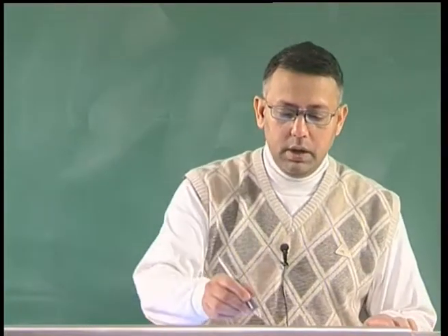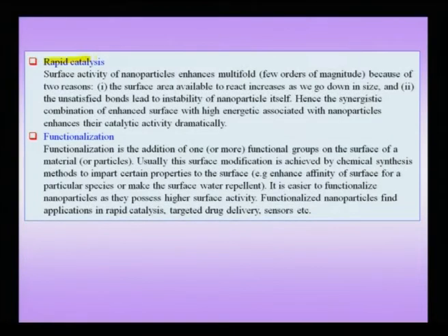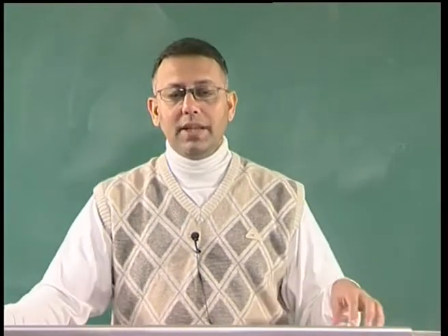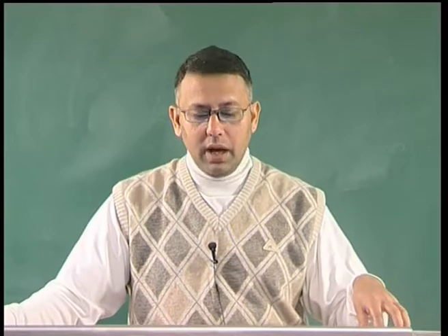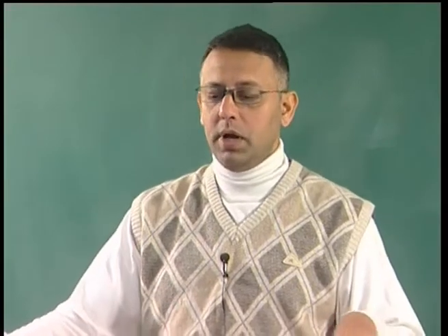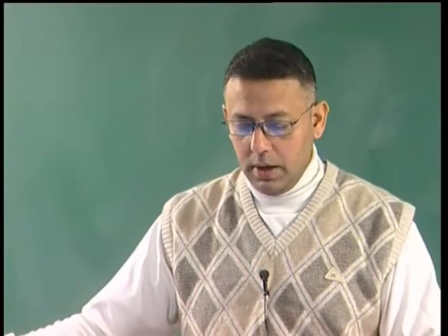We had already pointed out that increased surface area also means a high ability for a material to perform like a catalyst. The startling example is the case of gold. Gold in its macro scale typically does not have any catalytic role, but suppose I am talking about gold in the nano scale, embedded, for instance, in an Fe2O3 kind of substrate. Then you would notice that gold, which otherwise does not show any catalytic property, turns into a good catalyst and gets a lot of specificity in the kind of process that can be controlled with it when reduced to the nano scale.